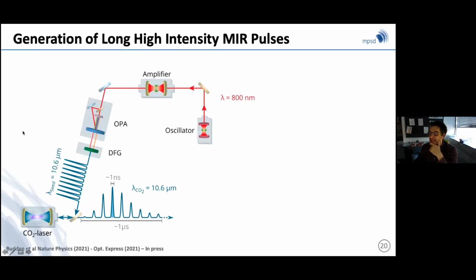What Matthias and Thomas did was they took titanium sapphire femtosecond technology, which operates at 1.5 eV radiation, or 800 nanometers. Let's talk in wavelengths here: 0.8 micron radiation. You can use some nonlinear optical techniques to generate 10.6 microns, seeding the CO2 laser, which of course would make those short pulses long because of the finesse of the cavity, and then generate a train of pulses which is well behaved and, most importantly, is absolutely synchronized to an external femtosecond laser.